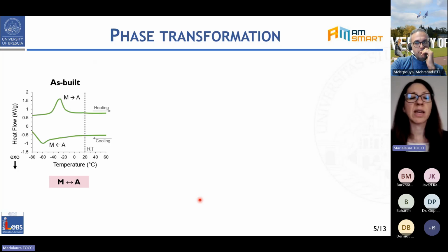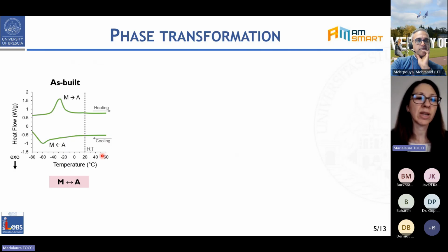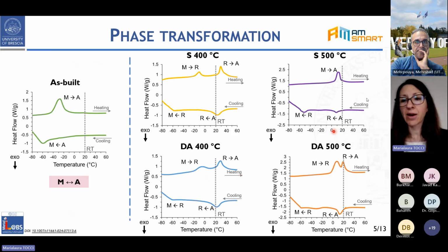So if we consider the identification of the transformation temperature, here we can see the thermograms for the as-built sample, and as you can see, we identify the martensite to austenite transformation at a temperature well below the room temperature. But what happens after the heat treatments? All the heat treatments applied were able to shift the transformation temperature to higher values.